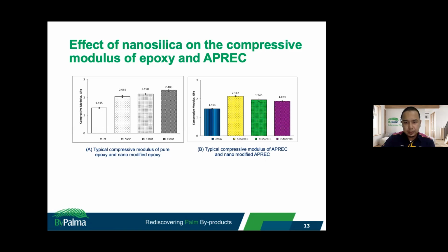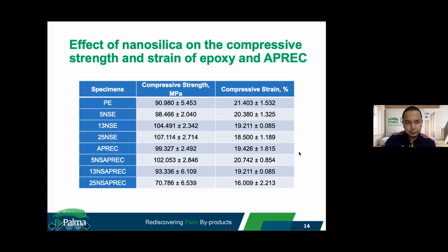This occurs due to the current formulation. The FRP composite became improperly wetted, as has been presented by my colleagues before this, because of the reduction of epoxy content in the composite.